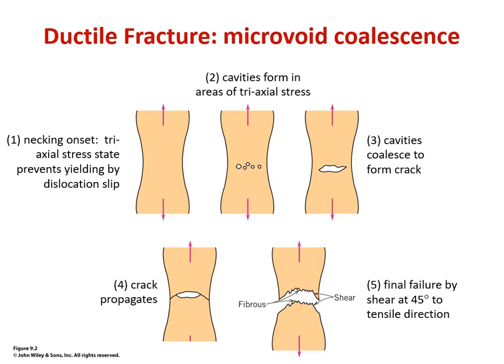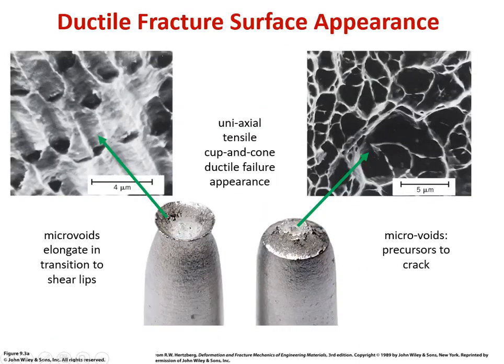This fracture appearance often goes by the name of dimpling or microvoid coalescence. And in the case of the latter term, that's actually a description of the mechanism. The microvoids that were pre-existing in the material grow under the action of increasing stress in our triaxial necked area. They coalesce until they form a crack that can propagate. And then the final failure around the outer circumference is shear. And here's what it looks like.